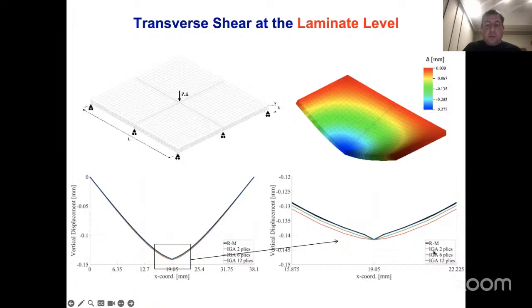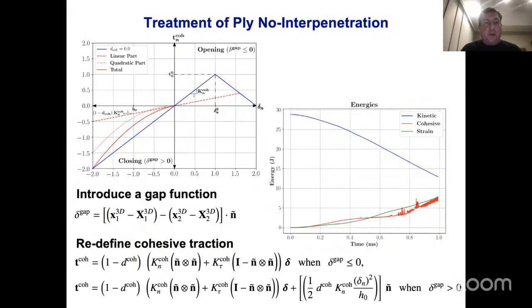If you're only using 2 plies, you completely miss it. But as you increase the number of plies, and as a result, you increase the number of cohesive interfaces, you actually match the Reissner-Mindlin solution at the end of the day. And so the conclusion is that while at the level of each lamina there is no transverse shear, once you put them together with cohesive interfaces, at the level of the laminate you recover appropriate transverse shear behavior. Very good.